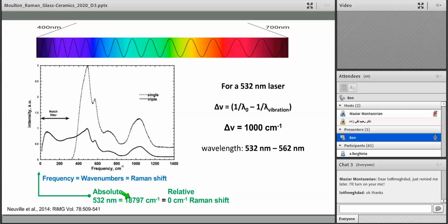18,800 or so. But there's actually the light that scatters without shift. This elastically scattered or Rayleigh scattering light will have zero frequency shift. So we need to have some filter, because we don't want to look at that Rayleigh light down here close to zero. If we had a vibrational mode, for instance, a peak here at 1,000 inverse centimeters, we could calculate what the wavelength of that vibration is by plugging this 1,000 inverse centimeters into our formula here, and we would see that this band correlates to a wavelength of 562 nanometers. So we have a red shift to longer wavelengths as you increase the Raman shift, and you have shifts to shorter wavelengths going to negative numbers in the typical Raman spectra.